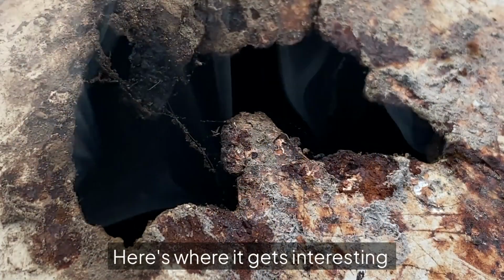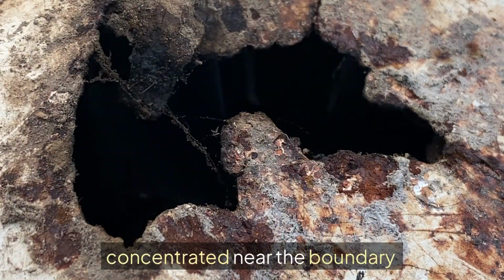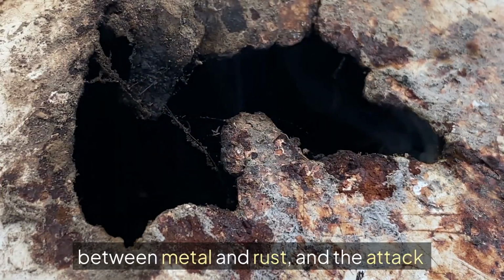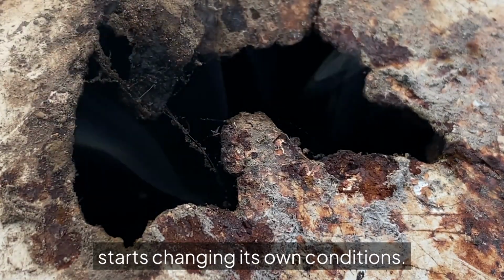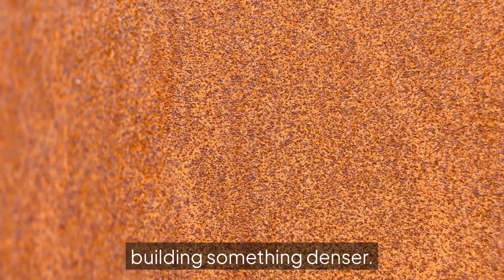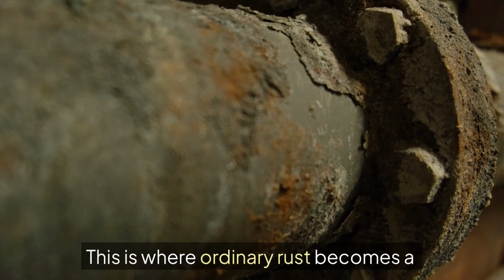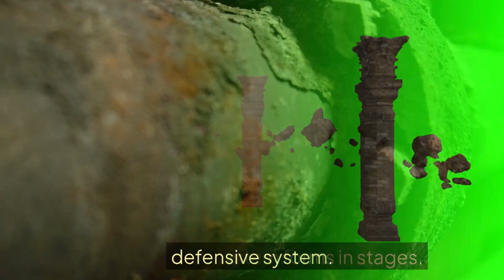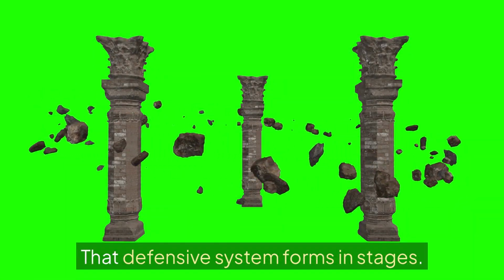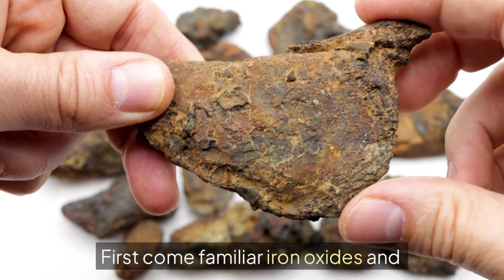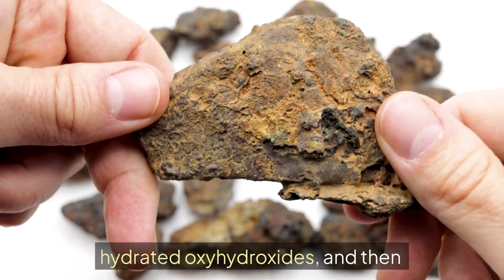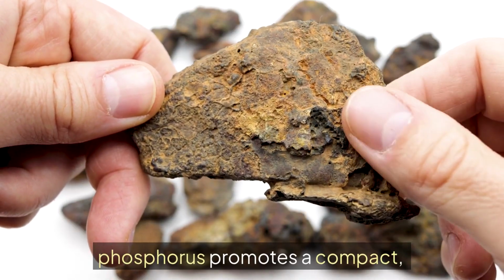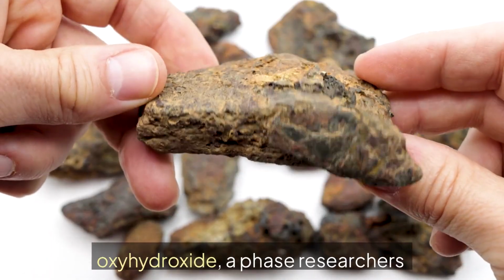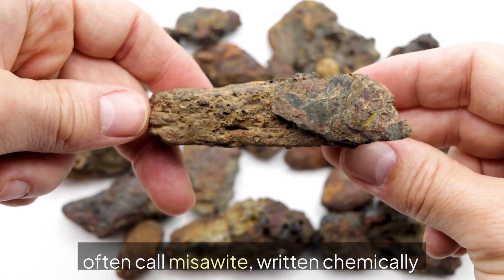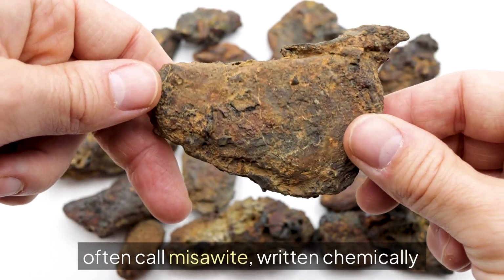Here's where it gets interesting though. Phosphorus becomes concentrated near the boundary between metal and rust, and the attack starts changing its own conditions. Rather than producing only loose, porous scale, the surface starts building something denser. This is where ordinary rust becomes a defensive system. That defensive system forms in stages. First come familiar iron oxides and hydrated oxides, and then phosphorus promotes a compact amorphous layer of delta iron oxide hydroxide, a phase researchers often call misawite, written chemically as delta-FeOOH.